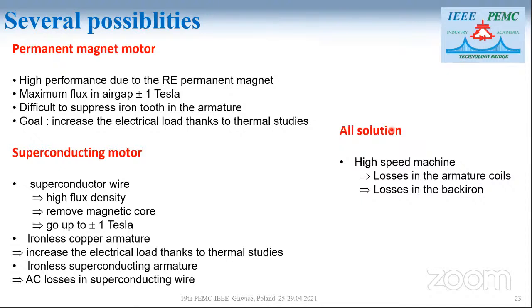So we need to make some assumptions, and we consider cooling between 20 and 30 K, for example, using liquid hydrogen as a cooling liquid at 20 K. For the rotor coil, you can operate with a current density of about 300 amps per square millimeter. It's easy to obtain. It's not an optimistic value, it's a conservative value.